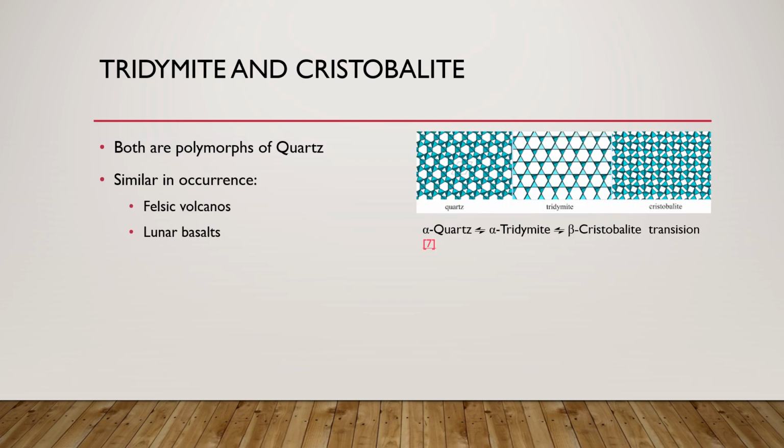Natural tridymite has no specific commercial use. Tridymite is stable at around 870 to 1470 degrees Celsius at atmospheric pressure. Tridymite can occur as a primary magmatic phase in siliceous rock, that is igneous rock largely or nearly entirely consisting of silica. Tridymite also forms in contact metamorphosed rock. Tridymite is also very common in cavities of felsic volcanoes, where it probably was deposited metastably from hydrous gases.